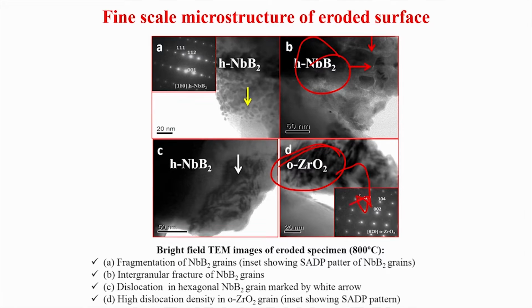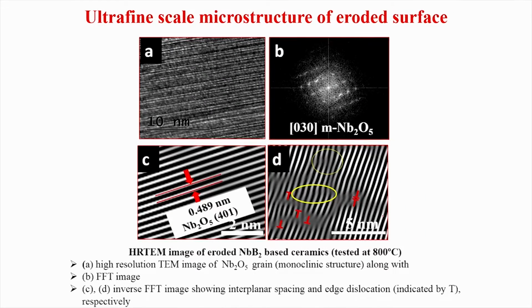And very confirmatory evidence we have got from selected area diffraction pattern, and this is what you can see here, that is the SADP pattern of this orthorhombic zirconia. Now, when you see this eroded surface, in that left hand image you can see the bright field image of this ultra fine scale microstructure of eroded surface, the surface scratches and so on, and you can see there is also signature of niobium oxide formation.